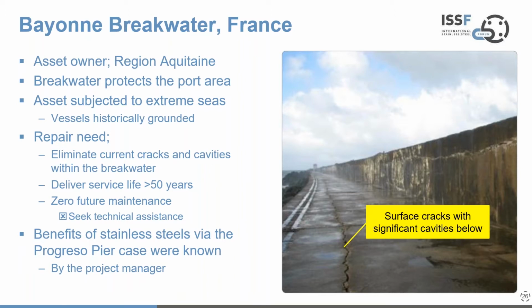So there's this breakwater. You can see a photograph of it on the right, and a nice crack running along the running surface of the breakwater. This was owned by Region Aquitaine, protects the port area, as I've said, and the asset was subjected to extreme seas. So what we had was a situation with cracks on the running face of the breakwater itself, where mobile plant went up and down, but also cavities below the surface and of a significant size. And a repair was needed to this breakwater.